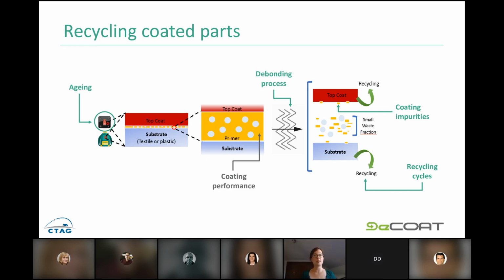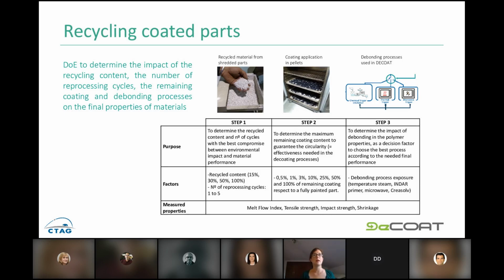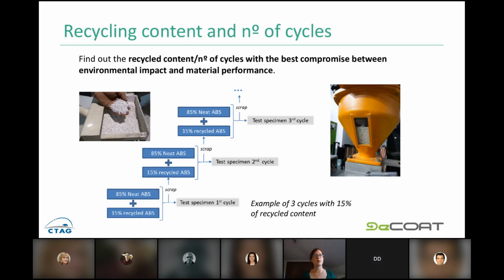So to assess all these factors, we have designed a design of experiment that takes into account all these factors and isolates them, just to know the effect of each one on the final properties. The first step is to assess the effect of the amount of recycled material, and also the number of reprocessing cycles. In step two, we add a controlled amount of coating impurities in order to see how the mechanical properties are affected. And in step three, we assessed the effect of the debonding processes carried out in DECOAT. I'm going to present the results, mainly focused on impact strength and tensile modulus.